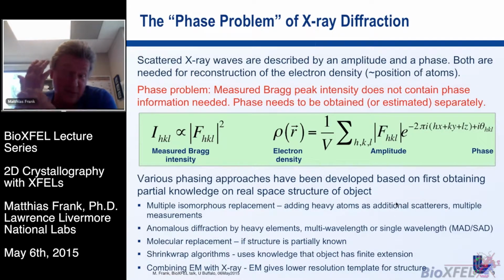For example, one of the problems is the so-called phase problem in X-ray diffraction, which comes from the fact that scattered X-ray waves are really defined by an amplitude and a phase, and you need both the amplitude and the phase for the reconstruction of the electron density. But the phase problem is that the Bragg peak intensity on your detector does not contain directly any phase information. So the intensity is really just related to the square of the amplitude, where the density is given by this equation with amplitude and phase factors in it.